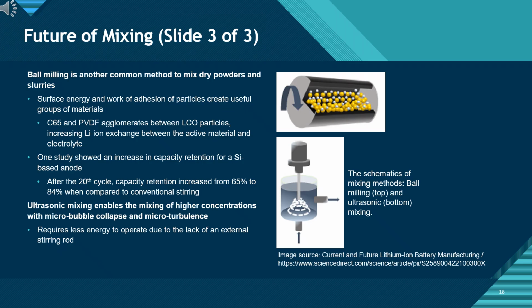For example, C65 and PVDF can cluster between LCO particles, improving ionic pathways. In silicon-based anodes, ball milling has shown meaningful performance gains. One study reports that capacity retention improved from 65% to 84% after 20 cycles, compared with conventional stirring.